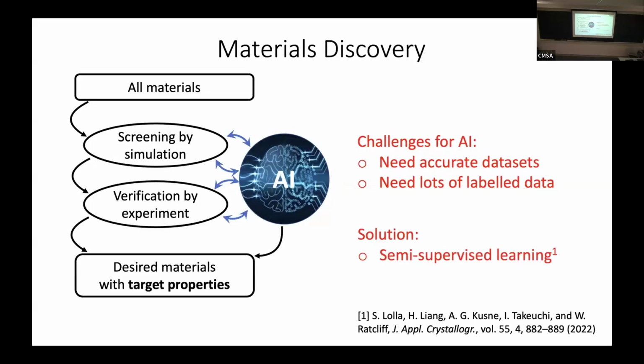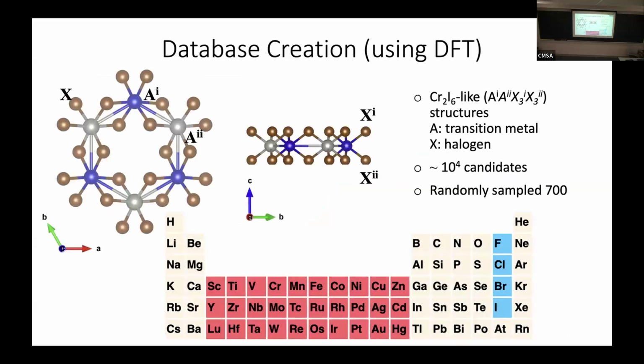So the solution I propose in the first part is to do so-called semi-supervised learning, also called self-supervised learning. I'll explain what that means in a little bit. So the first step is to create data, and we use these material simulations to do that on a supercomputer by taking our typical material, chromium triiodide, and we would decorate the A sites here with different transition metals shown here, and the X sites, the iodine above and below the plane, with different halogens. If you do that, we get about 10,000 or so potential candidates.